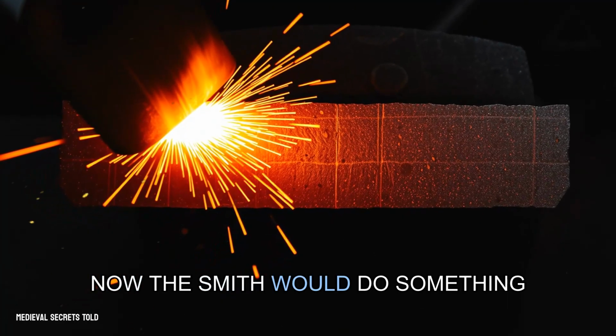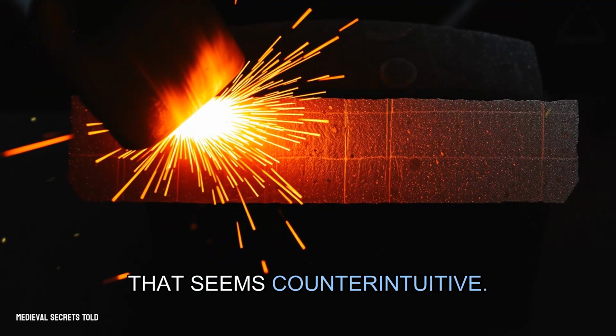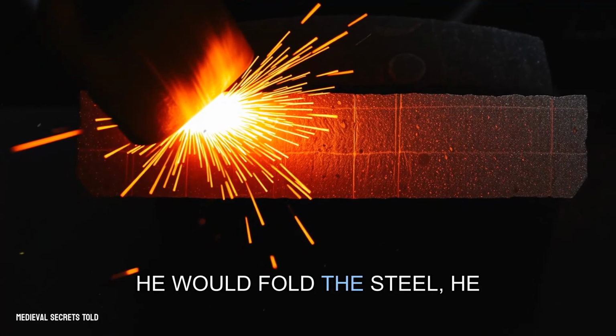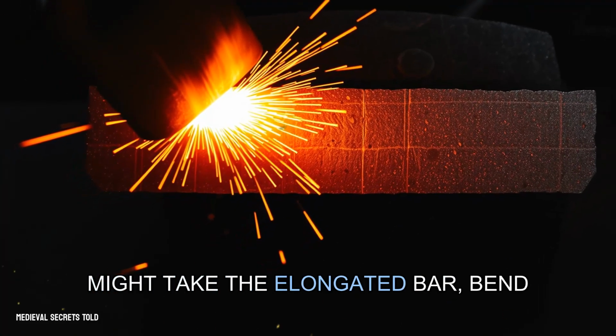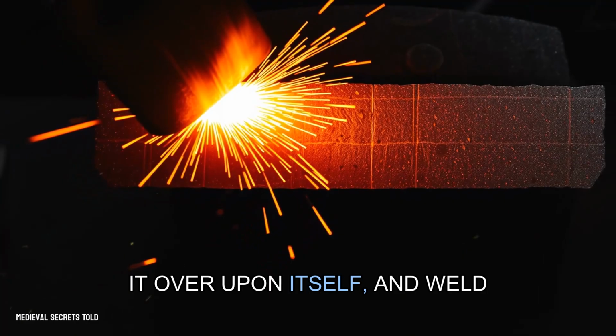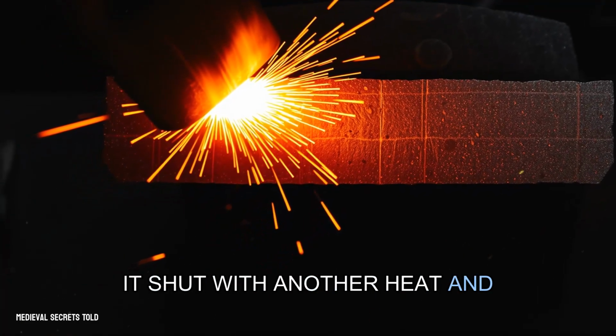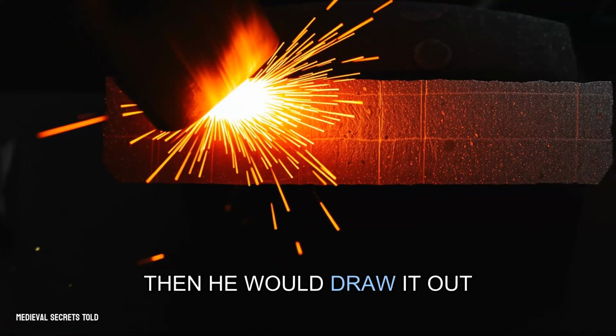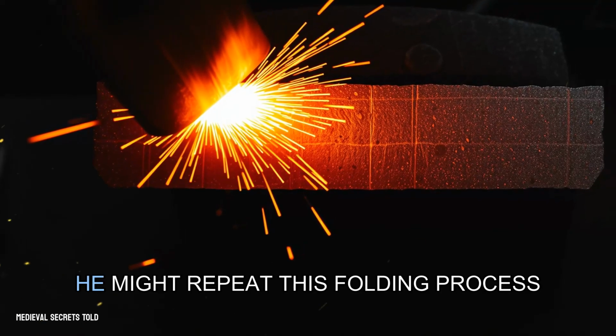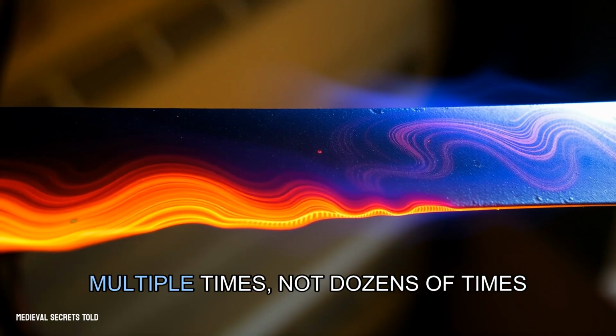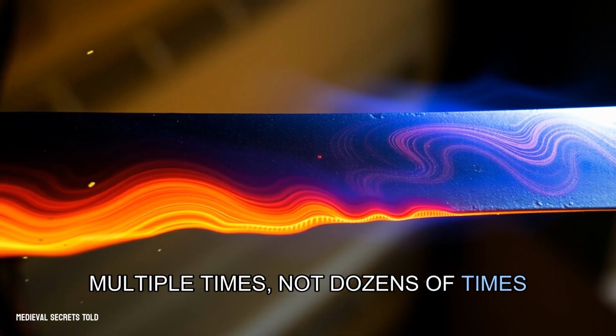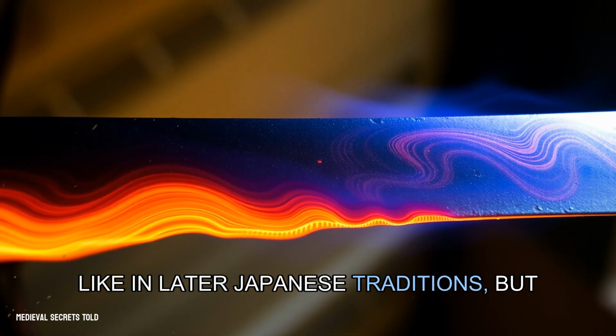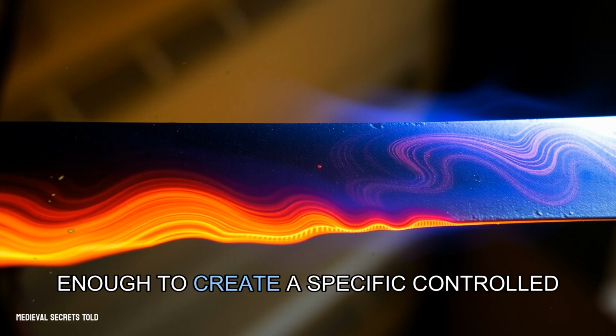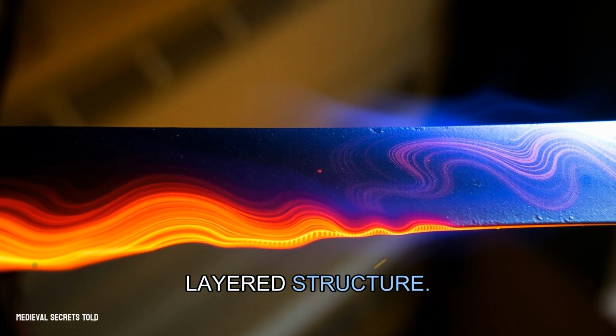Now the smith would do something that seems counterintuitive. He would fold the steel. He might take the elongated bar, bend it over upon itself, and weld it shut with another heat and hammer blow. Then he would draw it out again. He might repeat this folding process multiple times, not dozens of times like in later Japanese traditions, but enough to create a specific, controlled, layered structure.